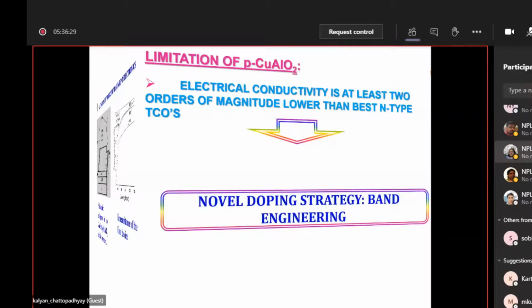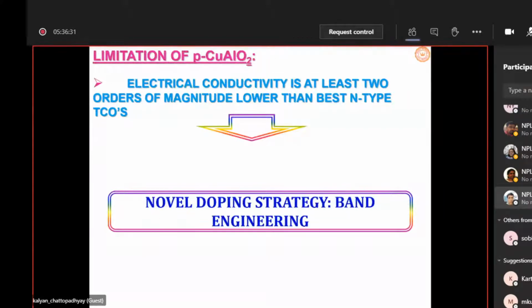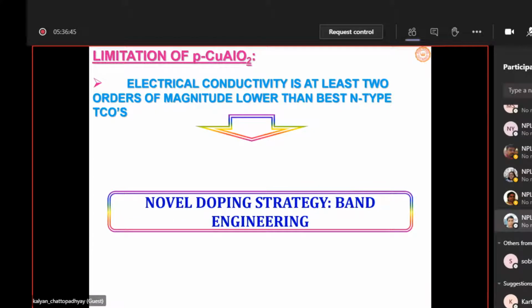But after 1.5 decades of research by our group and also some famous groups, for example, the Tokyo Institute of Technology group led by Professor Hosono, it is now evident that there are some inherent limitations of such systems, and the best electrical properties reported for this material are still at least 2-3 orders of magnitude lower than those of the best counterpart n-type material.